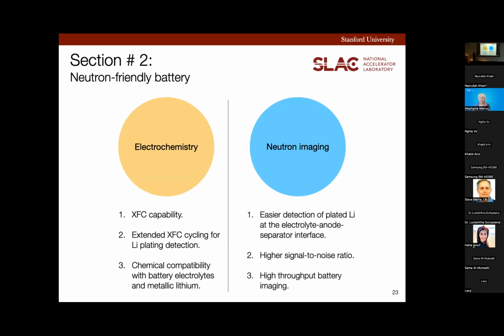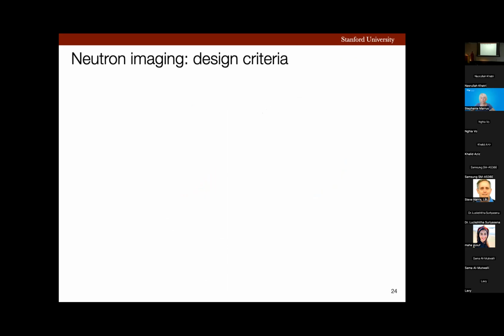Now, from the neutron imaging perspective, the battery should allow easier detection of plated lithium at the graphite-separator interface. It should allow a higher signal-to-noise ratio so that I can detect lithium with good statistics, right? It should also ideally allow high-throughput battery imaging. Now, my previous work made me realize that each neutron tomography scan takes several hours to complete. So if we can stack multiple batteries on top of each other, we can collect data in just one imaging experiment. Now, neutron imaging defines the design criteria for this battery.